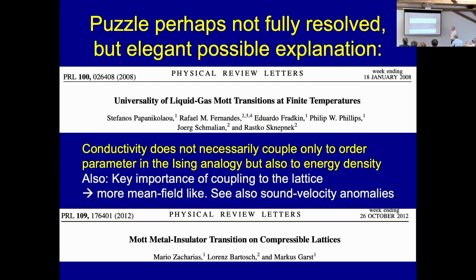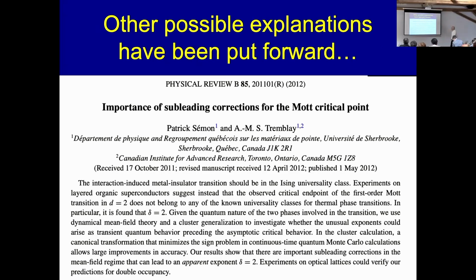This paper also emphasized something which has been studied intensively, in particular in the group of Michael, which is that the coupling to the lattice is actually very, very important in this problem and induces long-range interactions, which make it somewhat more mean field. That doesn't explain delta equal 2, but there are other possible explanations floating around, a little bit more mundane, but still interesting. In the group of my friend André-Marie Tremblay, they pointed out the importance of the subleading corrections to the Ising description, and in particular, the possibility of a very strong rotation of the scaling axis between field and distance to the critical point, and temperature and pressure. And they also claim that this could explain the BDT experiment.